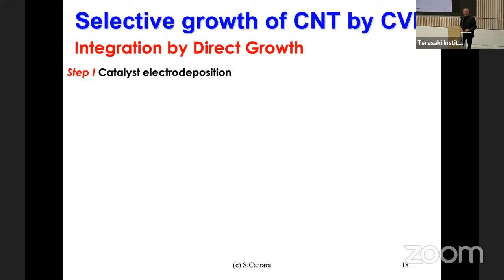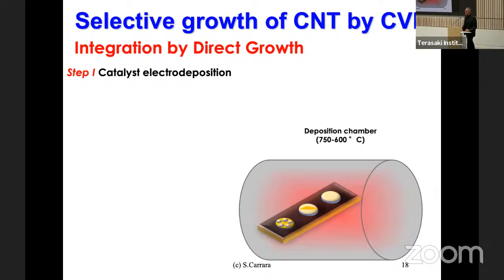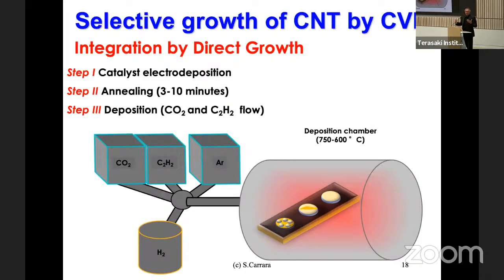How to integrate in our electronic system? Well, one way that we can do is to directly grow carbon nanotubes on our platform. So let's imagine having a multi-panel device with many sensors, many working electrodes. When I want to have my carbon nanotubes, what I can do is to pre-deposit a catalyst by electrochemistry, and then flux carbon-based gases. I can grow nanomaterial on top of my multi-panel devices. Another piece of bad news is that I need to do it at 700 degrees. If I do it on CMOS, I'm burning all my electronics. So no way again to do it like that.